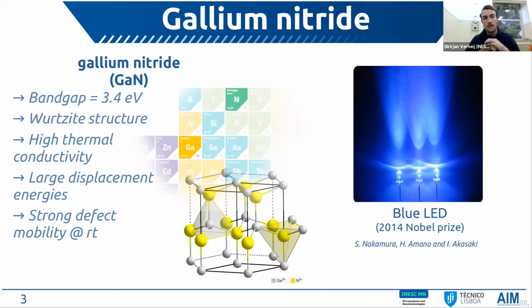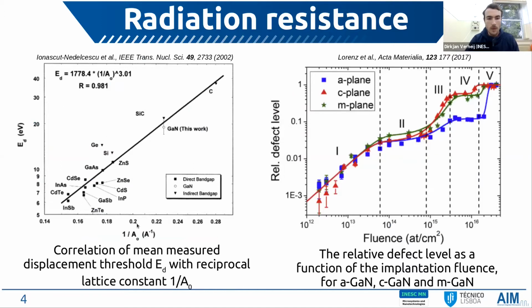And gallium nitride has a lot of very interesting properties. It has a wide bandgap of 3.4 electron volt, which makes it essentially blind to visible light. It typically grows in a wurtzite structure, which is a hexagonal crystal lattice, as we can see here. It has a high thermal conductivity, a large breakdown field, but especially important for radiation applications, the atoms in the crystal lattice have large displacement energies, and the material presents a strong defect mobility at room temperature. And I'm going to show you here why these characteristics are important.